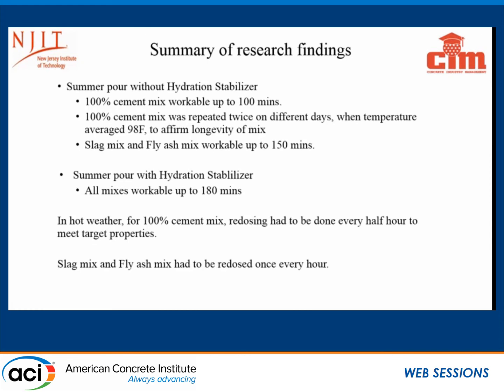This was our first try, basically, our first foray into the research on the 90-minute rule. So going forward, we have a better idea as to what dosage rates will more closely reflect the desired outcome. Generally when you establish data and you have historical performance, you will know what dosage rates to use. For example, from my experience back then, we already knew what dosage rate of retarder we'd use depending on what type of job we're pouring, where we're going and that sort of stuff, because I already had the historical data. Here we are just developing it for the first time and we're going to build on it. So a lot of the questions that have arisen and will arise, we'll be answering as we go along in terms of making additional tests and presenting the data.